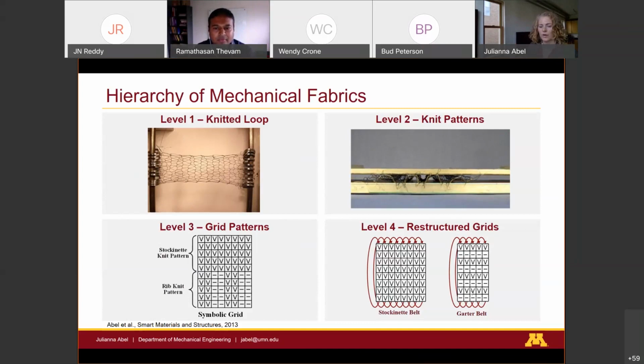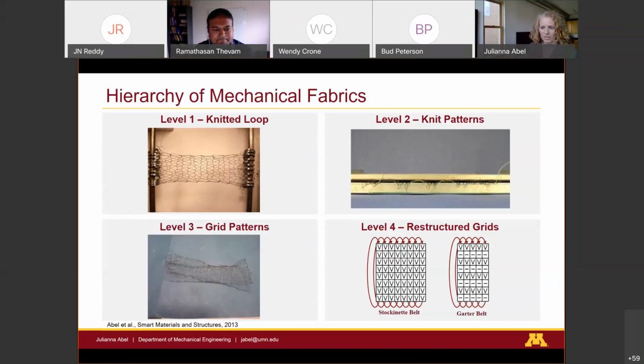The next level is creating heterogeneous patterns across the surface. And so we have grid patterns. This is half rib and half stockinette. So the rib portion accordions in one direction, and then sequentially the stockinette comes over and folds. So we get sequential actuation with spatially distributed motions in different areas.